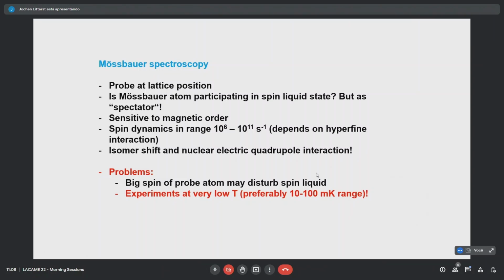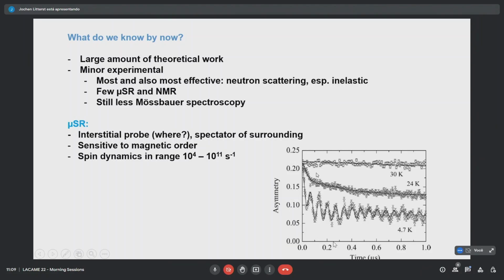So let me go back to that here. I only want to show you, for those who are not so familiar with the method, where the muon signal comes from. If we implant a muon, it has a spin 1/2, and inside magnetic fields the spin will start precessing. It may be sitting in its internal field, if the material were magnetically ordered, and that's detected if we implant polarized muons, and the polarization of the muons will change with time. These are the oscillations which you see here in the magnetic state. That's detected by an angular correlation experiment.